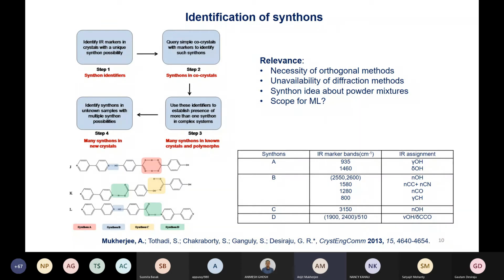So coming to the technique, what we did, we first tried to identify synthons from a known group of compounds, and then we applied it to the synthons in the co-crystals. Then we tried to take many synthons in known polymorphs and co-crystals, and then try to identify some unknown co-crystals in the 4th stage. So here is a pictorial depiction of the possibilities which can happen in synthon polymorphs if you take a hydroxybenzoic acid and a bipyridine ring.